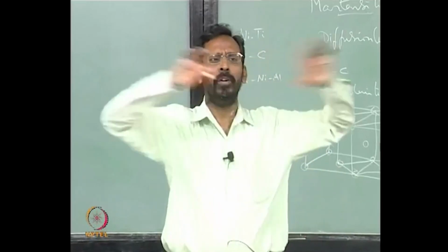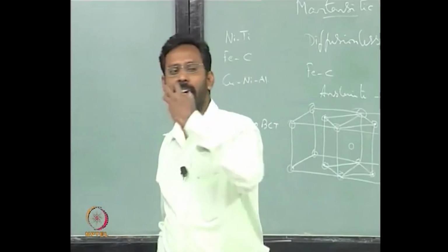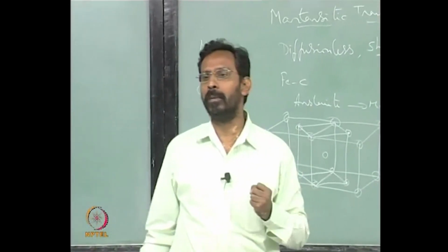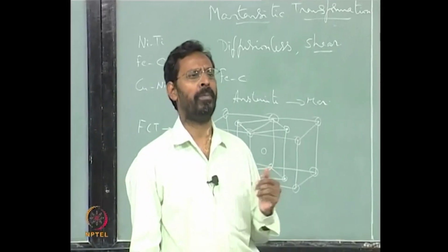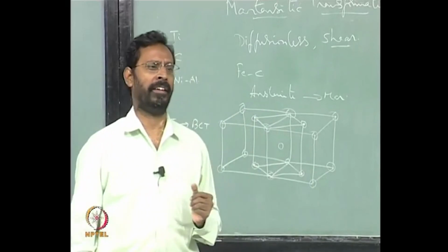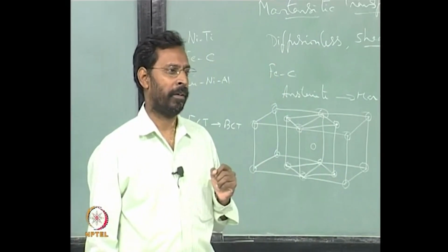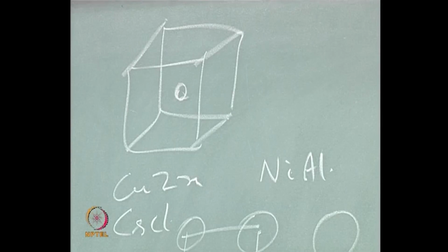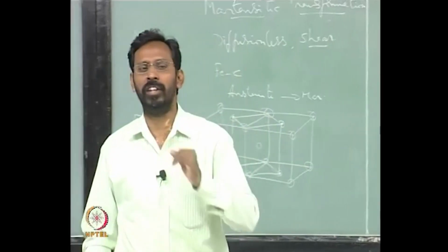Once all the corner atoms are occupied by copper and all the body center atoms are occupied by zinc, I cannot call it BCC any more, because the body center position is not copper again; it is zinc, whereas the corners are copper. So we say there are actually two unit cells there, one unit cell made of copper atoms, another made of zinc atoms.